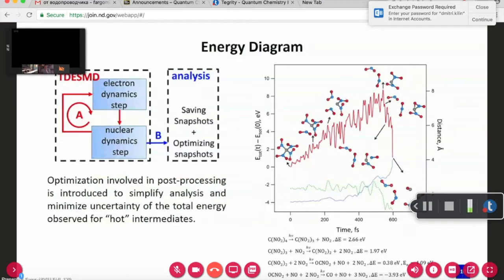As we can see, the starting point is the tetranitromethane molecule, and the final product is gas phase components. So we have 3 nitrogen dioxide molecules, a carbon monoxide, and a nitrogen monoxide. And the activation energy for this reaction is about 4.1 electron volts. And actually this final product is very consistent with experimental findings. Next, please.